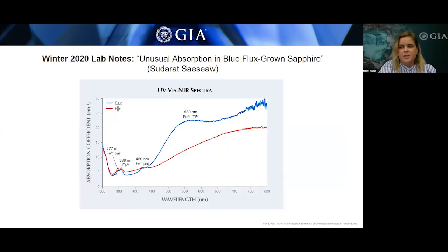However, the most interesting feature of this stone was its UV-Vis-NIR spectrum. The spectrum had the usual 377, 388, and 450 nanometer peaks, which are related to iron, and then an Fe2+/Ti4+ broadband around 580, which is responsible for the blue color that you see in the stone.